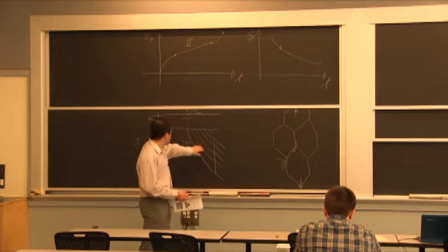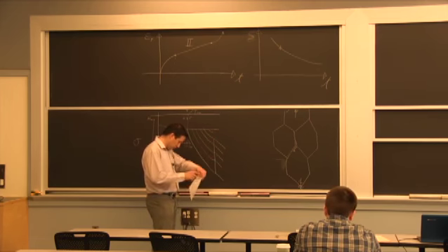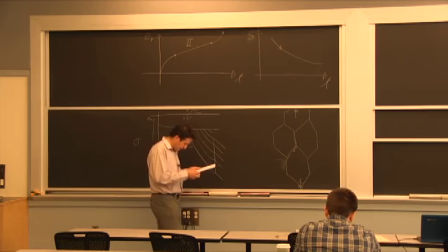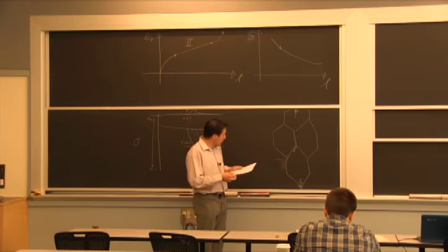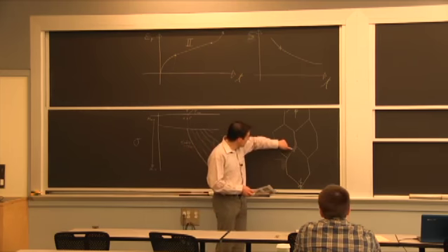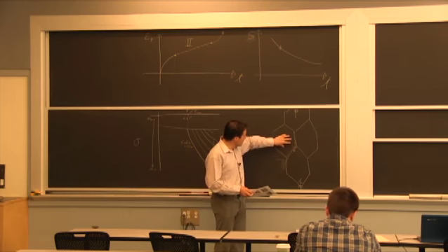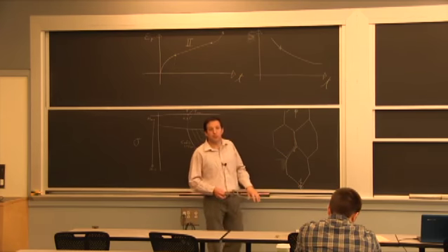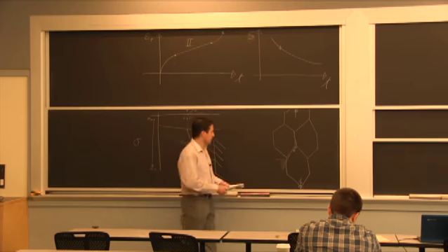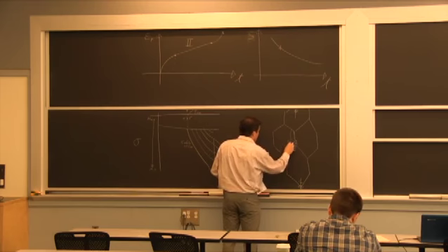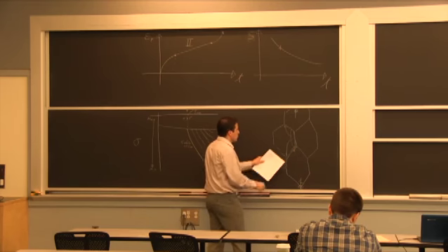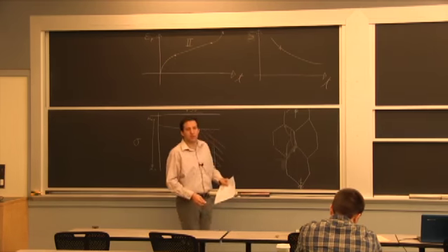Now I made this line here that goes to, if you go to the slide, the Nabarro creep. What happens at a certain temperature is you're not only going to diffuse to the grain boundaries, but your diffusion in the grain will become more significant. So start taking material from this whole area and bring it over here, bring it over there, through the grain as opposed to the grain boundary.